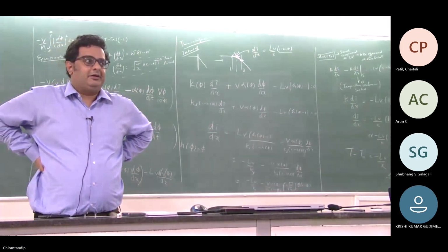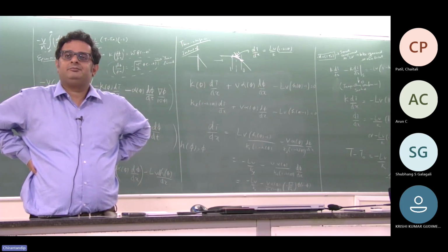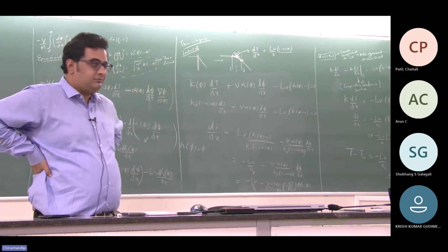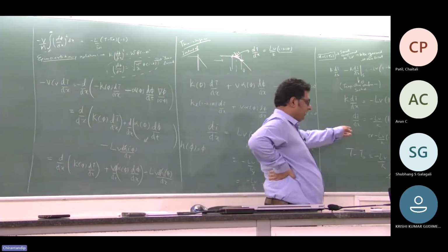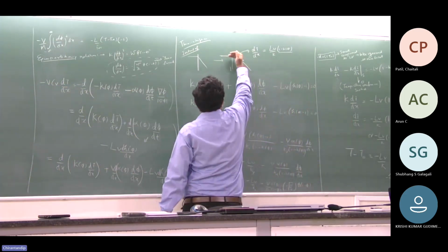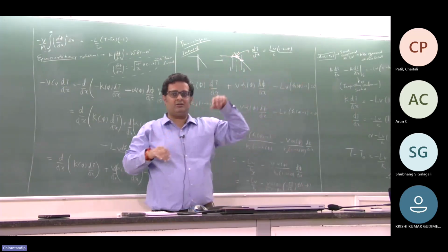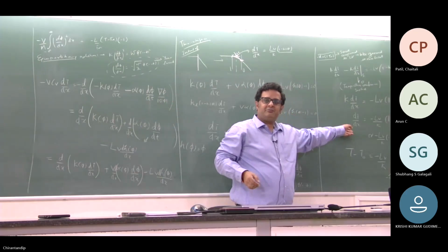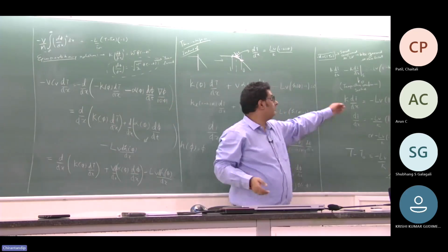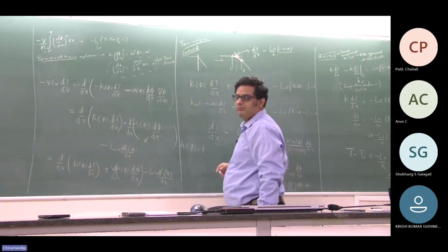Right? Any questions? From this, can you say anything about the temperature profile across the interface? Does it follow the h of like dT/dx? It will exactly follow now. Because I did the correction, I am going here now. dT/dx will essentially go to 0 here, 1 minus h by here. But the temperature profile does not correspond to the T star equal to T naught asymptotic that we derived, right? It will, because of this now. Because of this correction, now T star, which is the asymptotic value from the liquid, will exactly match T naught.